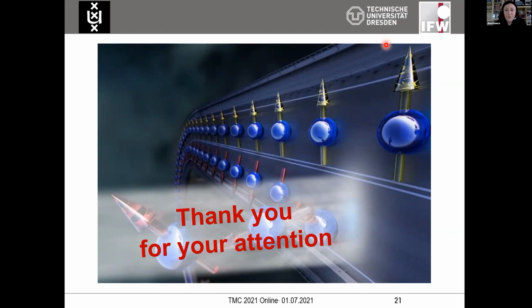Thank you very much. So as far as I understand the present state of the literature, there is no considerable disorder reported for manganese bismuth telluride films. I'm aware only of MnBi2Te4 grown periodically as a thin film. There are problems, but if there is disorder, it's minuscule, it's not really being discussed. But in this arXiv preprint that I flashed by on the last slides, about the MST film, manganese antimony telluride film, yes, there is disorder. It was deliberately looked at. It's about 5 to 10 atomic percent in each position. And these are also over-stoichiometric samples, so they have an excess of manganese. That apparently very much changes the properties. They also report a very high TC of about 45 to 50 K.